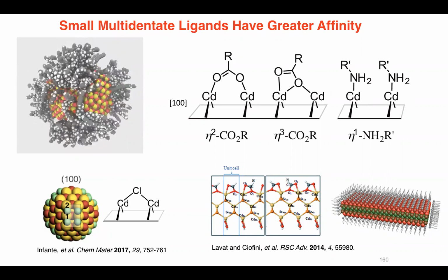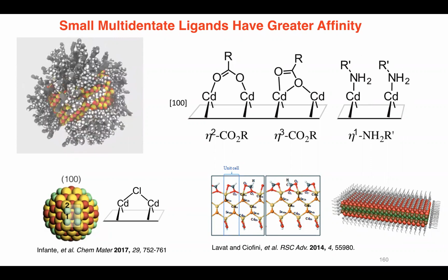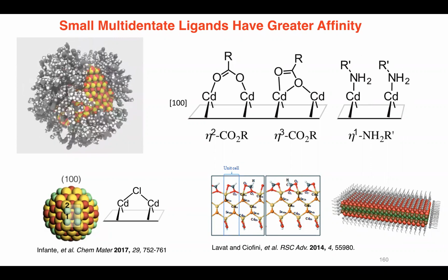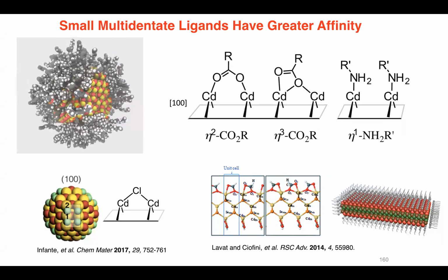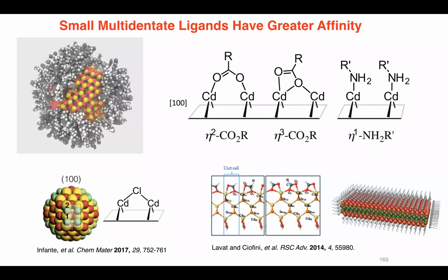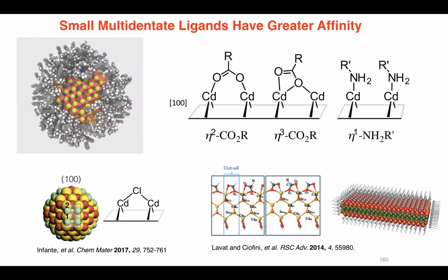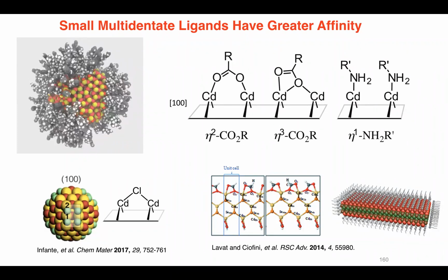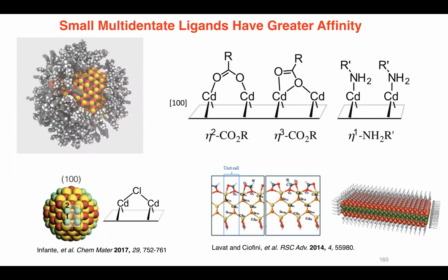The coordination number of cadmium ions is dependent upon the covalency of the ligands that are bound to it. So with thiolates, you'll go to 4 coordinate structures. With hard ligands like halides or carboxylates or amines, you'll go to 6 or 7 coordinate. So this thing here is very odd. But you have a ligand packing problem on surfaces, right?